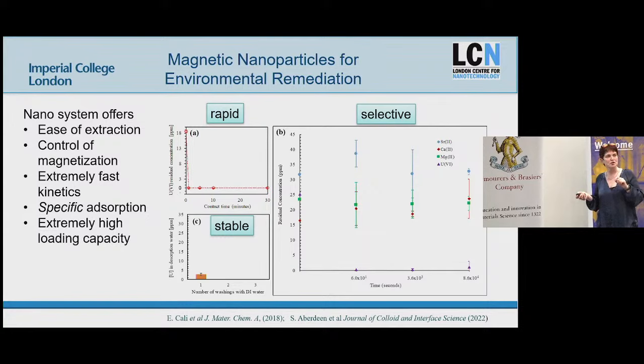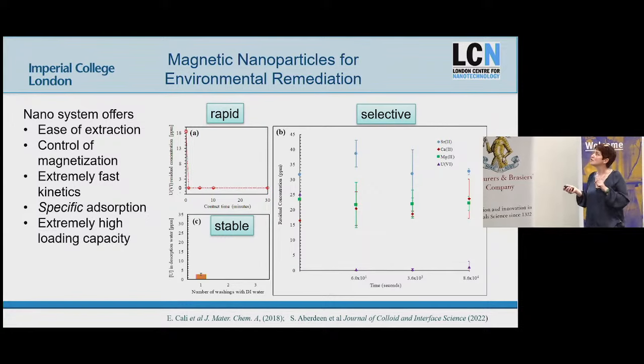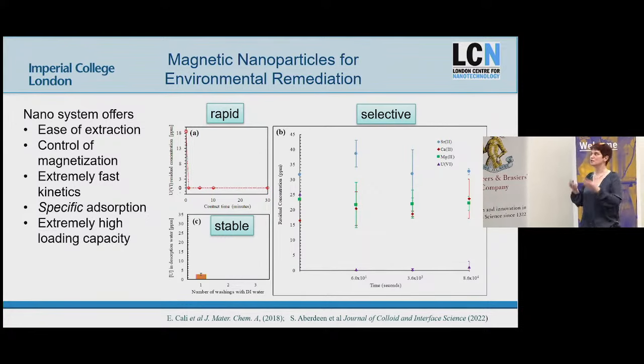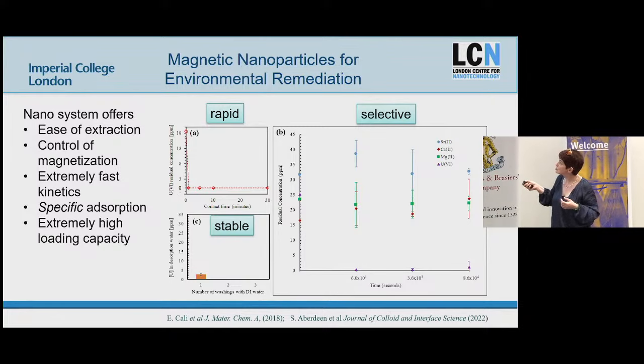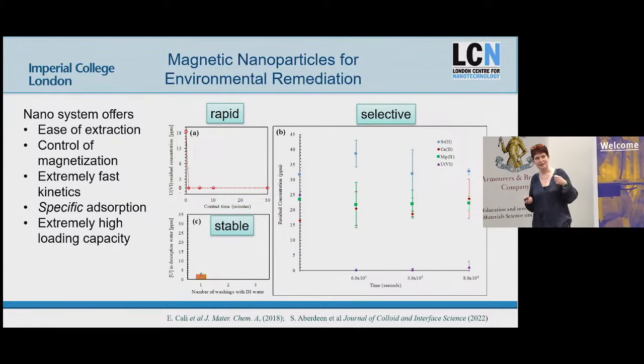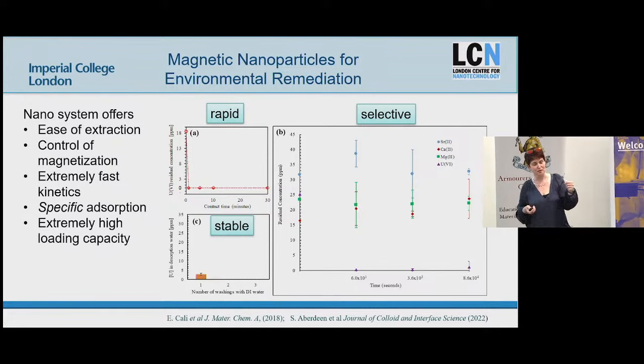And what we were most surprised at, it's really selective. So if you put those nanoparticles into a mixed solution of, here we use strontium, calcium, and magnesium, and we picked those elements because that's what some of the Sellafield fuel ponds have. So we started off with a bunch of stuff. Uranium goes to zero. Everything else pretty much stays the same. So you can design your surface and your surface chemistry and your magnetic particle to go in, grab the thing you want to take out, pull it back out, extract it, and have clean water.